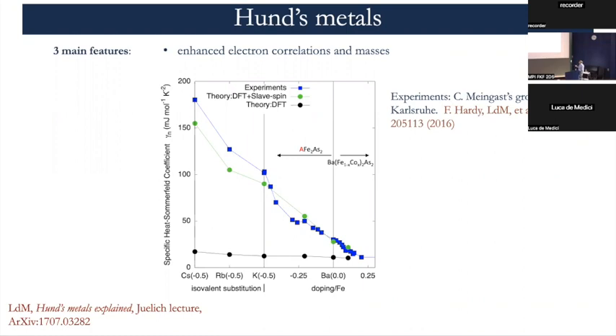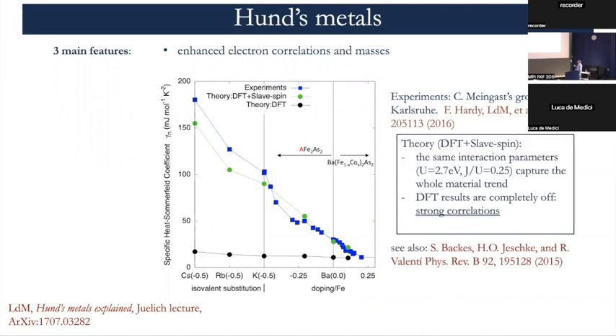And you see that the blue points here are going up and up and up. These experiments are done in the Karlsruhe group of Christoph Meingast. And if you do DFT, you have these black points. So that's where you know that the compounds are strongly correlated, because these results of DFT are more and more off the more you go on this hole-doped side. Whereas if you do DFT plus slave-spin with just one value of the interaction strength, you get this green curve, which tells you that correlations are playing the role to get this density of states up, and that Hund's coupling is key. If I take out Hund's coupling, all this disappears. So it's really Hund's physics.